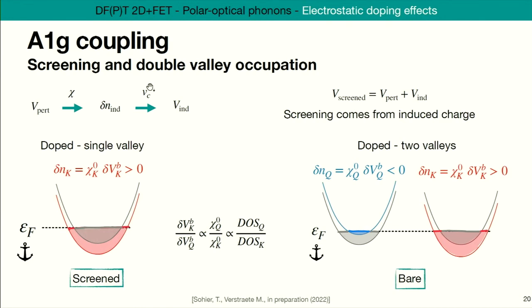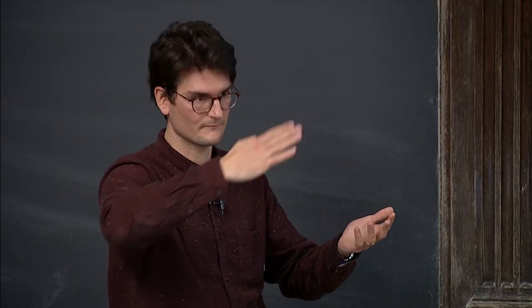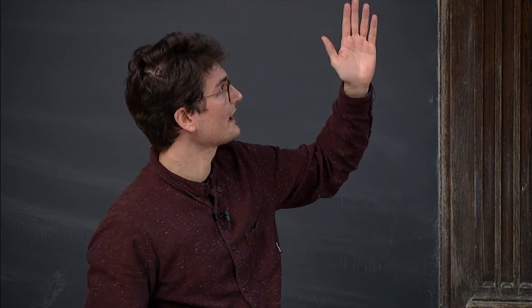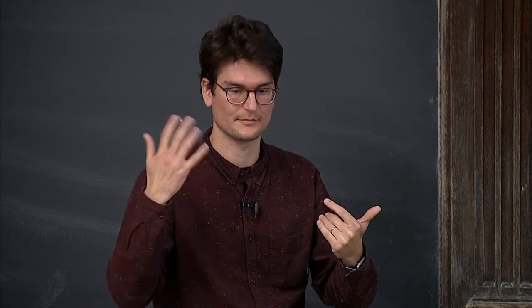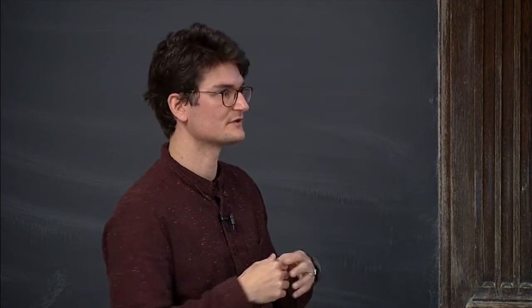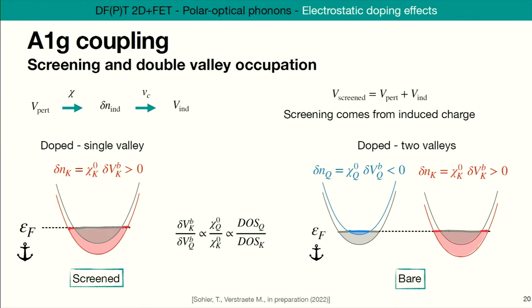So let's look first at the single valley case. We said that when only one valley is occupied, we don't have this softening. That's rather easy to understand. If we imagine just one valley going up and down in energy, like in this plot here, we forget about the second valley. It's too high in energy. It doesn't matter for the electrons. They don't see it. So we have only one valley going up and down. We need to keep the Fermi level constant. That's always the case. And you have the valley going up and down as a function of space. You need to remember this is a phonon, so it varies periodically as a function of space. As it goes up and down, the filling of the valley is going to change. This corresponds to a variation in the charge density. So there is an induced charge density. It's going to be periodic, and so there is an induced potential, and there is screening. So this kind of perturbation is screened.